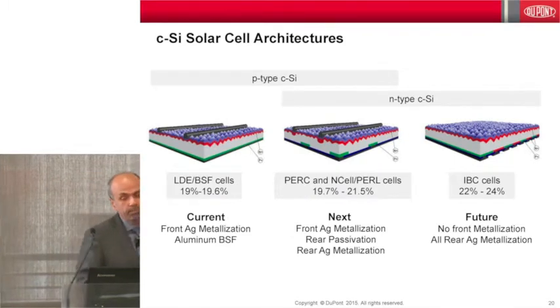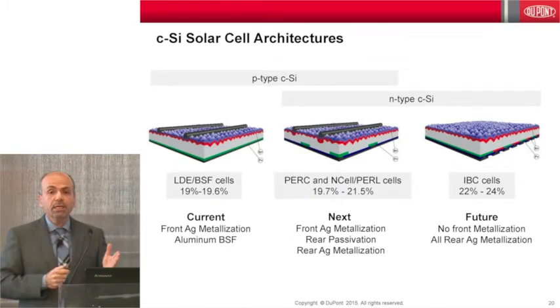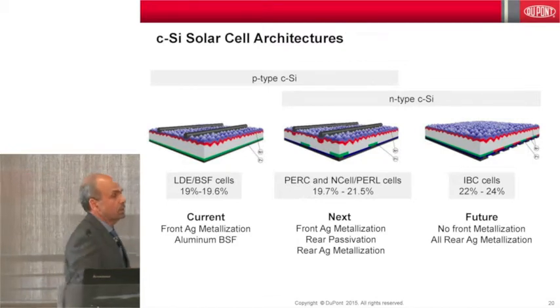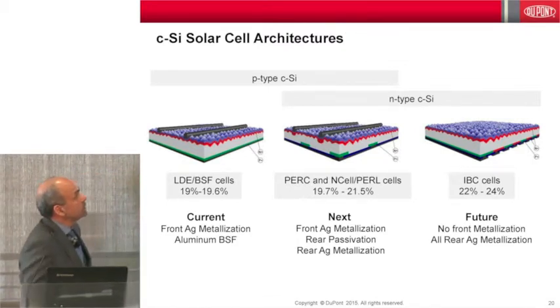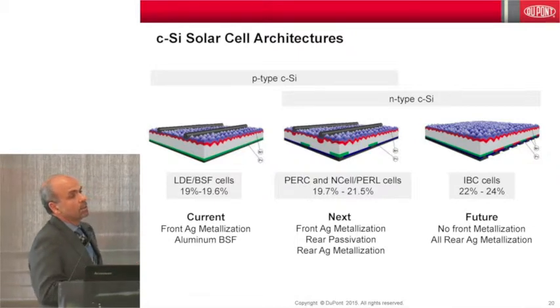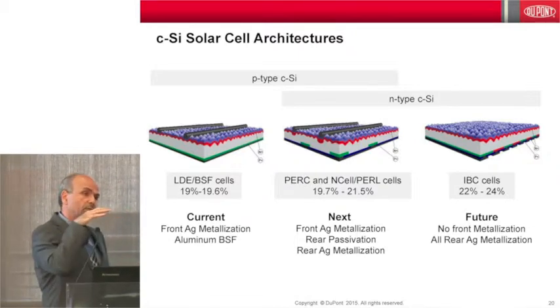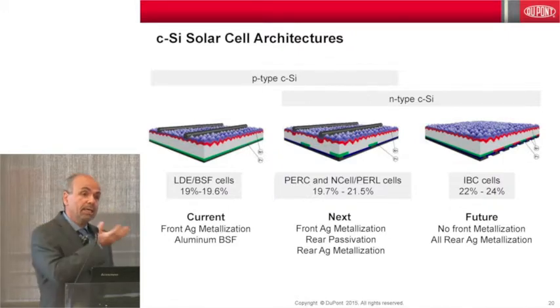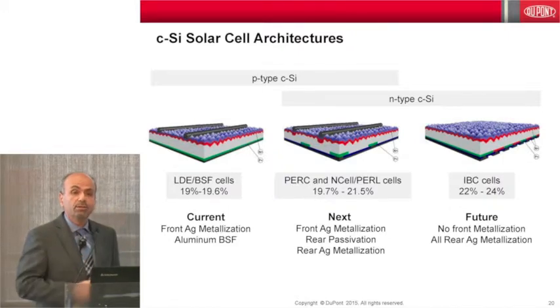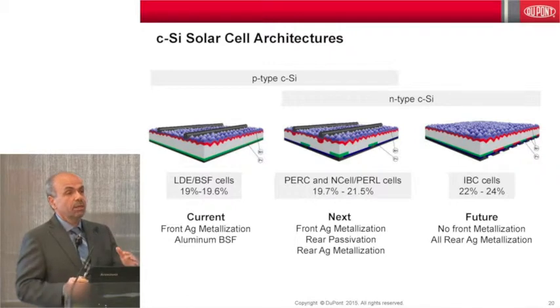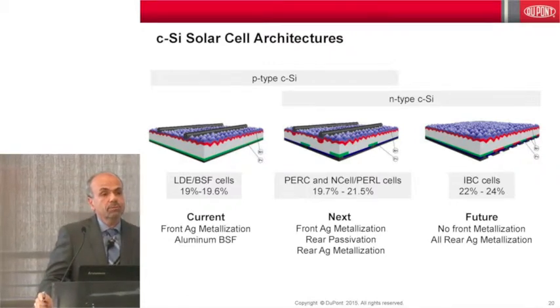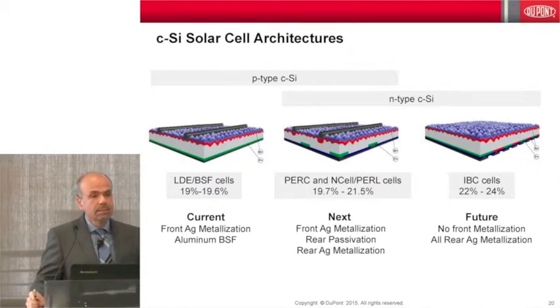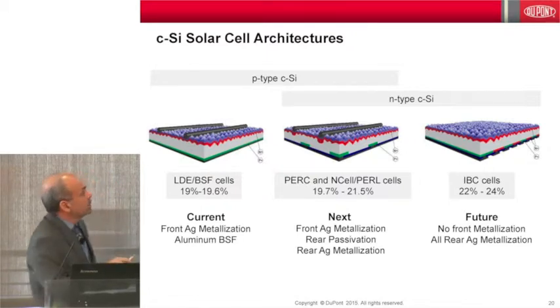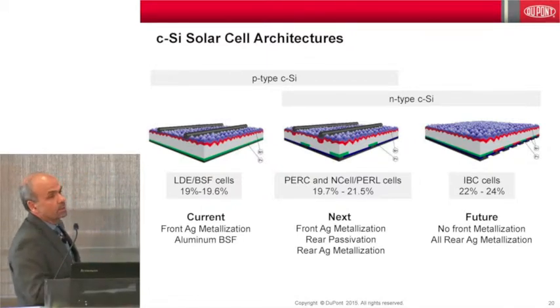So what happens with the designs, with the crystalline silicon designs? As of today, the majority of the industry has been using a very traditional design where finger lines are going on top and a blanket of aluminum paste is screen printed in the rear. Now, this device structure has been extremely successful, and more than 95% of the crystalline silicon panels out there follow this design. It's very reliable, but it has some limitations. The aluminum that you have in the rear